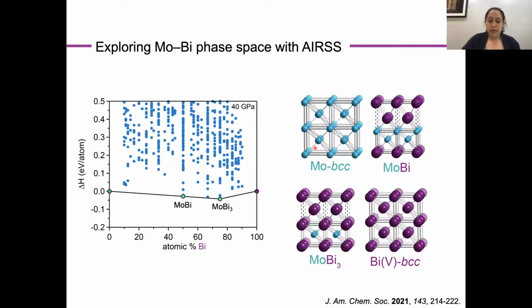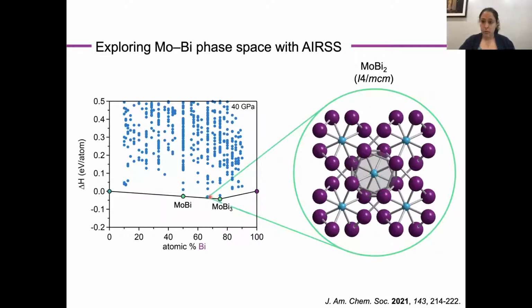But in doing this analysis, I also came across this structure here, which falls at the 1-to-2 stoichiometry. And you can see here that's quite distinct from that BCC motif. This is a beautifully ordered structure based on square antiprisms of bismuth surrounding chains of molybdenum that go back into the plane of your screen. And this was readily recognizable as the copper dialuminide structure type. This is a very common structure type. It's shared by over 100 combinations of elements across the periodic table. And very importantly, has also been found for other high pressure combinations of transition metals with bismuth.